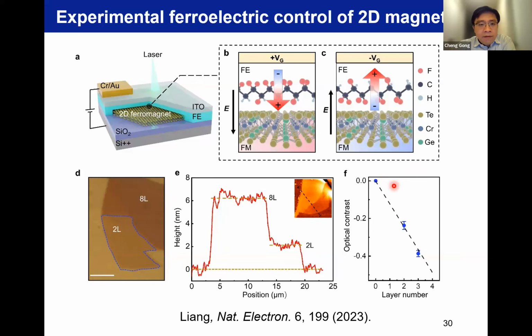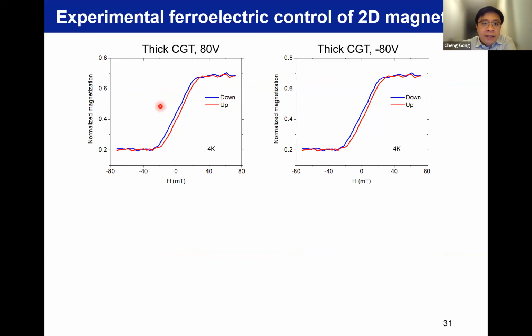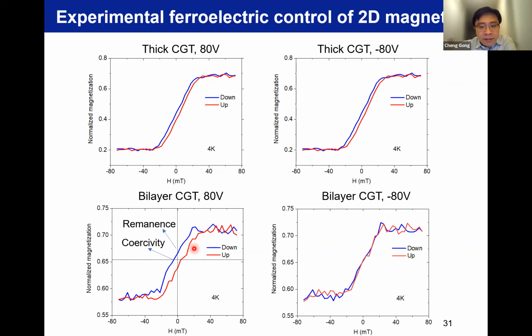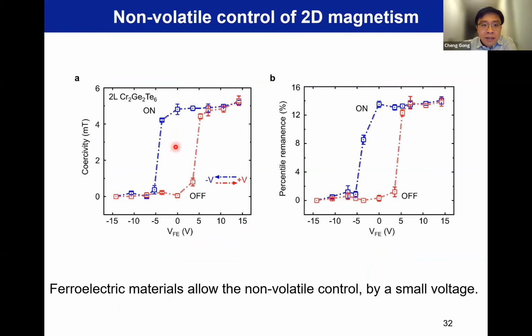You can see in figure D, you have 2 layers and 8 layers, using these two regions. For this 8-layer CGT, when we apply positive and negative voltage, you do not see a clear change in the hysteresis loop. But for that 2-layer region, you can see a clear opening and closure of the hysteresis loop. By keeping track of the remanence or coercivity, we have voltage-dependent coercivity and voltage-dependent remanence. It's non-volatile, so certainly this is because of the ferroelectric polarization.